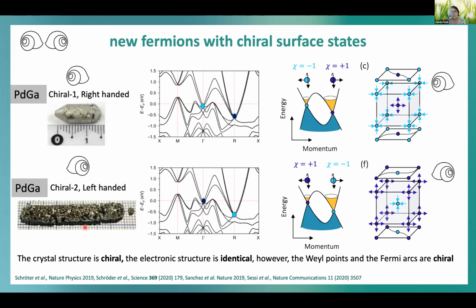So we have 2 different chiralities in the crystal structure, but the band structure is just the same. But we can assume that the Berry phase, so the electron momentum, which is locked here, has different chirality. So one time it should have this chirality, and in the other case it should have that chirality. And but we cannot distinguish this in a simple band structure.